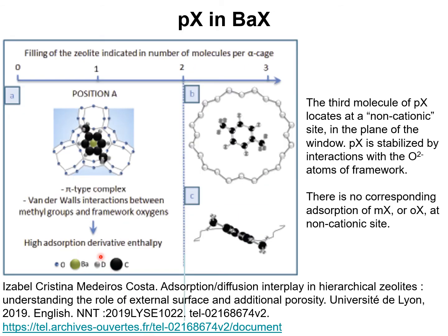In contrast to meta-xylene, the placement of the third molecule of para-xylene within BaX is not energy demanding, because the longer para-xylene molecule can be located in the plane of the window and is stabilized by interactions with the oxygen atoms of the framework.